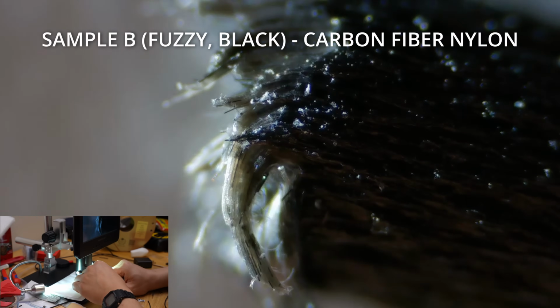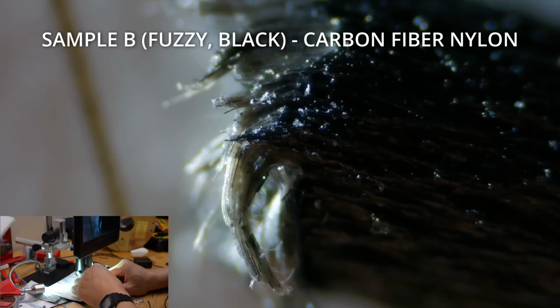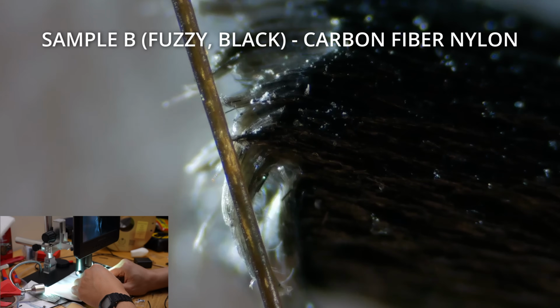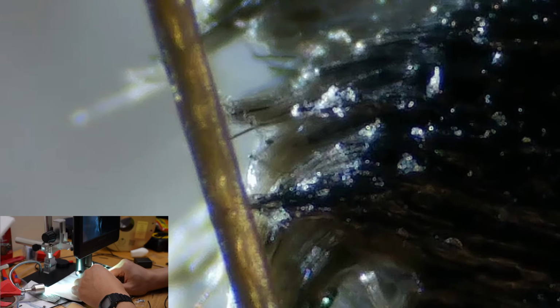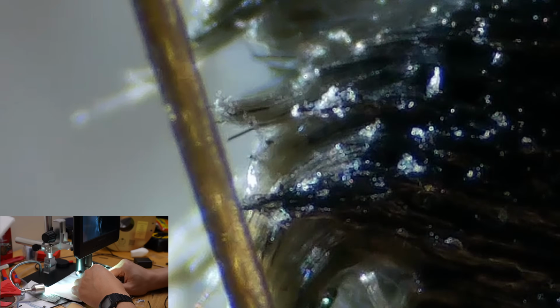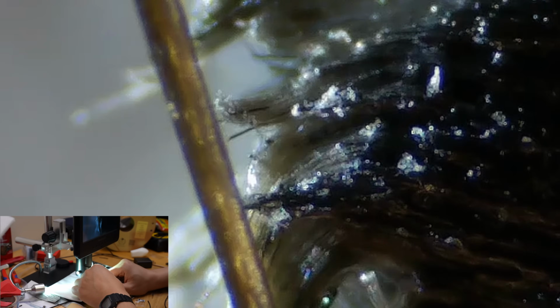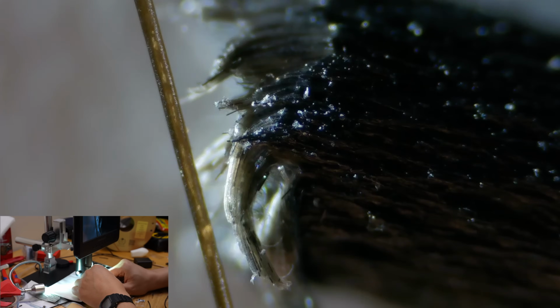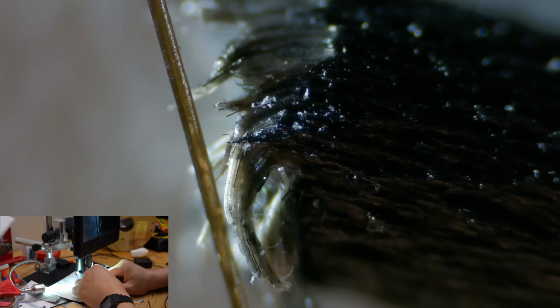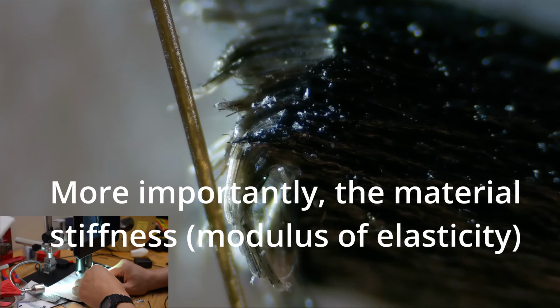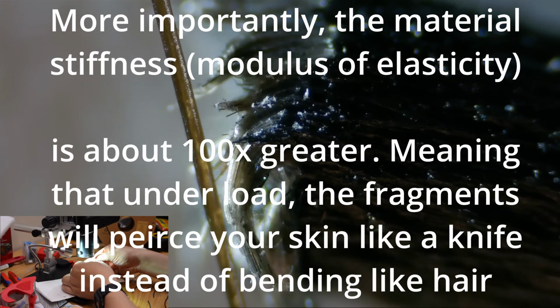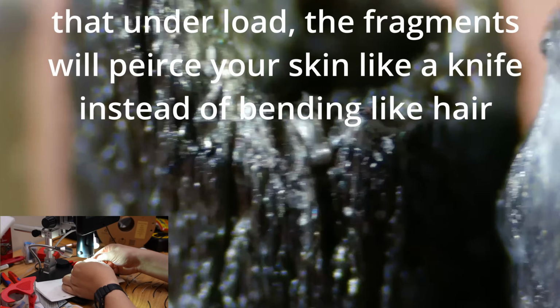And just to give you some context for the size of these little fibers, this right here is a human hair. So you can see the carbon fibers are maybe a 20th the diameter of a human hair. Your body is used to dealing with hair, but these carbon fibers are an order of magnitude smaller. This is a Bambu Lab PA CF. So let's move from sample B to sample C.